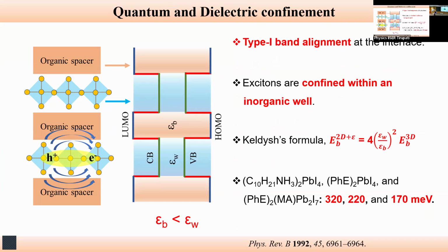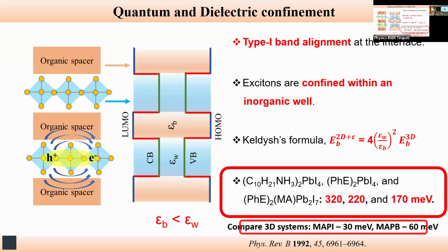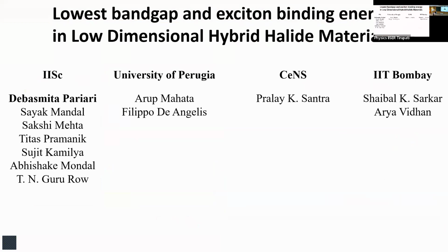You can see that the excitonic energy of this kind of two-dimensional objects is in the order of hundreds of milli-electron volt, compared to the three-dimensional ones in the order of 30, 60, 70 milli-electron volt. So I gain the environmental stability, but I lose the energy. Also, because of this very confinement, the band gap tends to increase from the optimal value. So as I'm going towards increasing environmental stability, I'm losing the other two good attributes of small band gap and small exciton binding energy. And this led one of my students, Debashmita, an exceptional student.